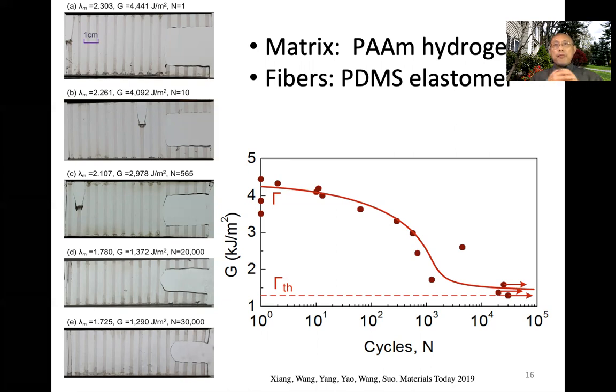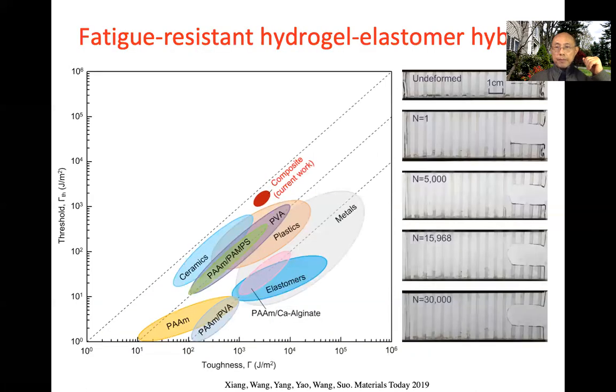The point is, even for natural rubber, the best threshold we know about is about 50 joules per meter squared. However, for this composite, the materials we use are just lousy materials, PDMS and hydrogel. The threshold reaches 1,000 joules per meter squared. There is a lesson. So we keep going, and we compare with our material. This is a plot of threshold and toughness. For our material, the threshold is comparable to toughness, right? For natural rubber and all these elastomers, the threshold is much lower. We already said it's on the order of maybe 100 or 50 joules per meter squared, even though your toughness is very large.